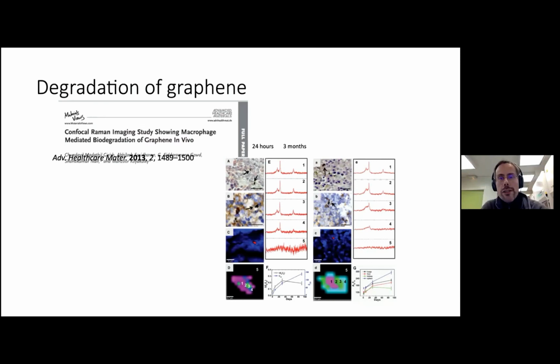This is the first reason. The second one is that in a polymer which is loaded with graphene, you have many more edges and nanoparticle leaching out. So in terms of cytotoxicity, it's another problem. The dose makes the poison, like we say. So here, the amount of graphene presented to the wound, in terms of volume that can potentially leach out in the body, is completely negligible. It's less than a nanogram per centimeter squared.